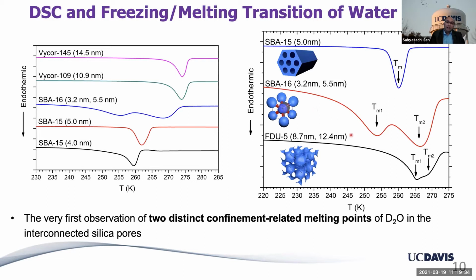So this behavior of two different melting points was quite interesting because this indicates a tremendous amount of dynamical heterogeneity in the water confined in these nanospaces. That tells me that, when I go to SBA-16, the water in these 3.2 nanometer cylindrical pores is not talking to the water in the 5.5 nanometer spherical pore.